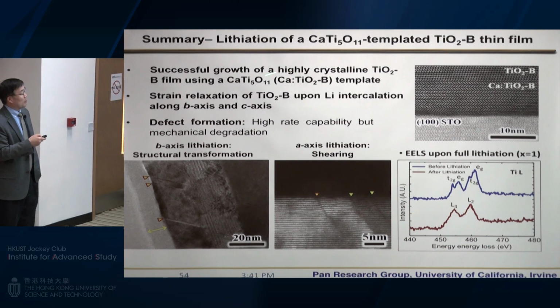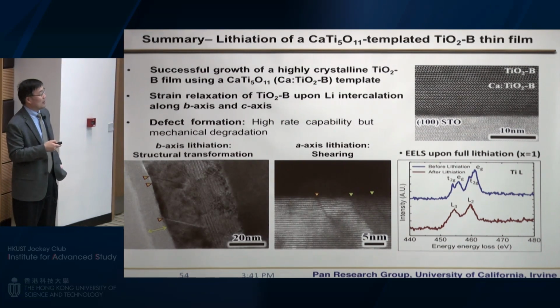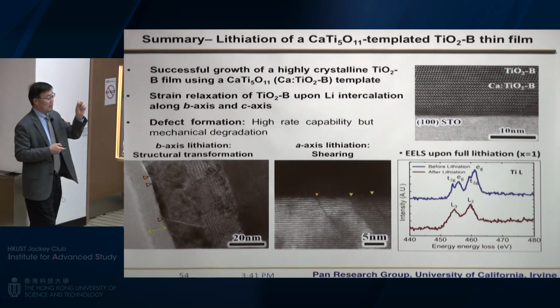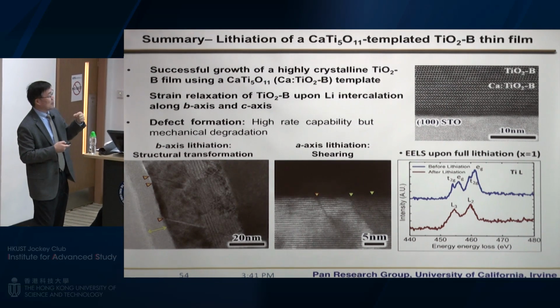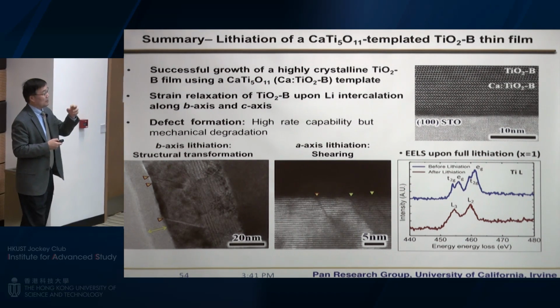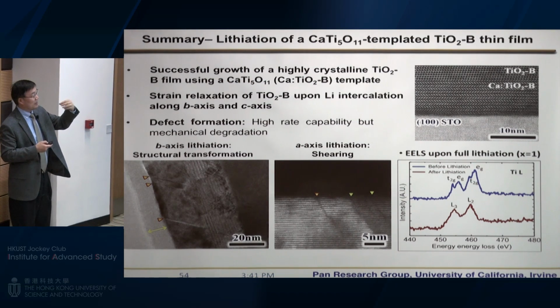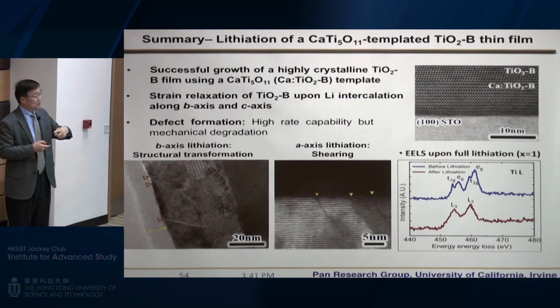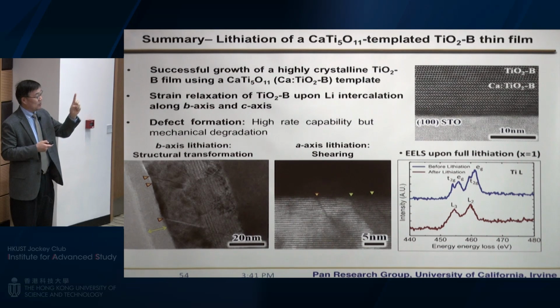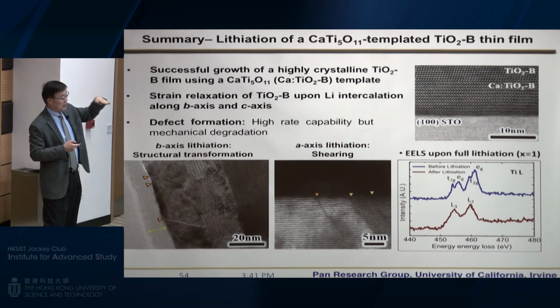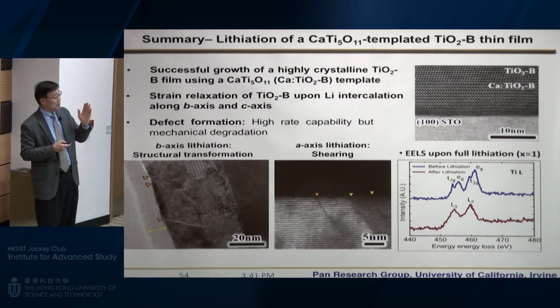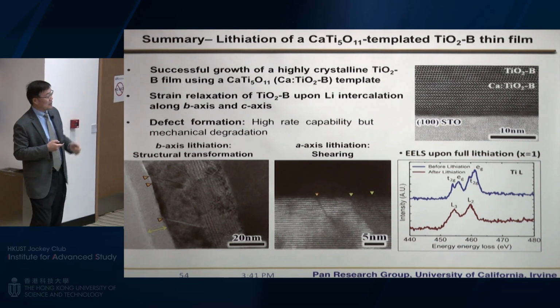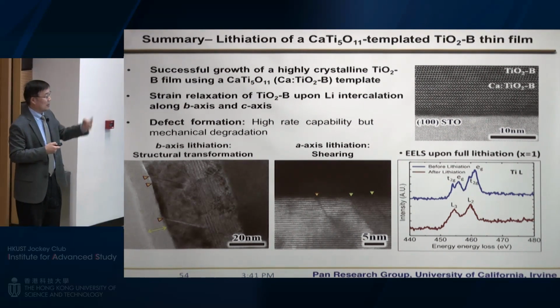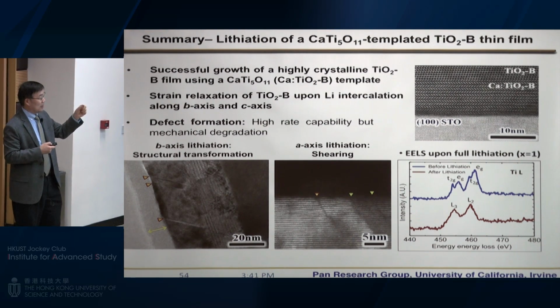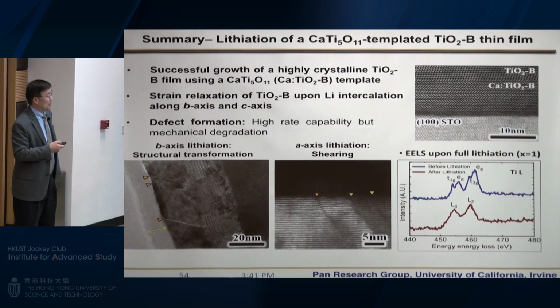And then for the bronze B structure, so we have two kinds of bronze B, calcium doped, and also pure TiO2. Pure TiO2 has a little bit higher capacity than bronze B. But bronze B, we can make two different kind of texture. One with diffusion channel in plane, another is out of plane, so that we can test the difference in the lithium diffusion on different channels.